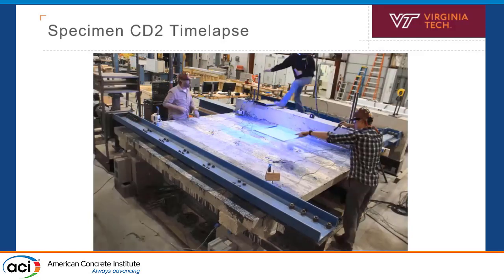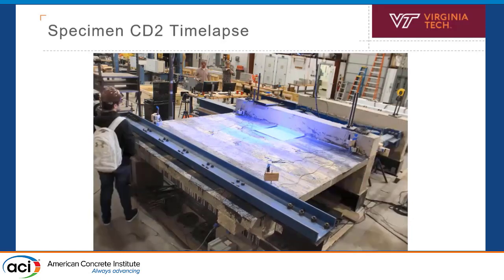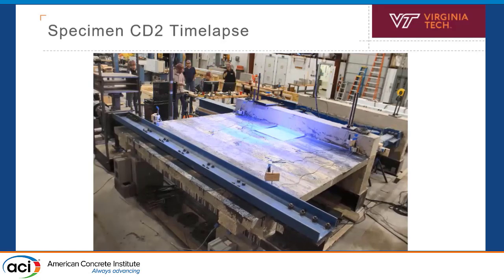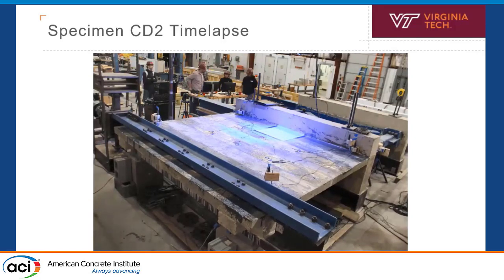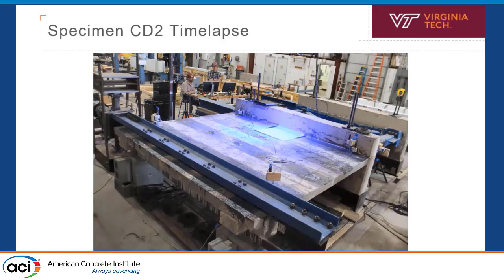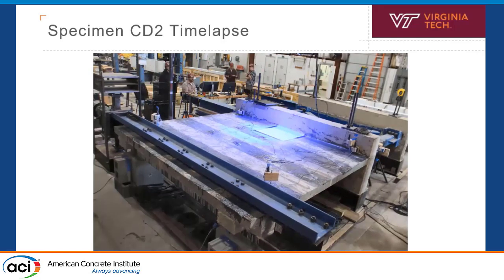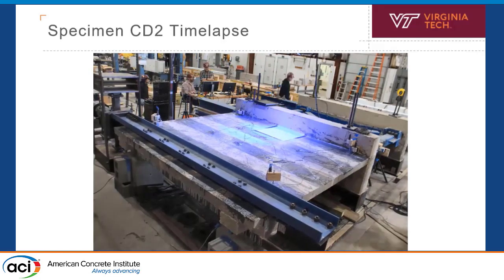And that can happen in two ways. The epoxy can fail between the concrete and the laminate, or your epoxy can be so strong, your force so high, that you can yank your top cover off. And that's what we experience predominantly here. Since this is a 4-inch slab, we have half inch cover just peeled right up at about 0.004 strain.